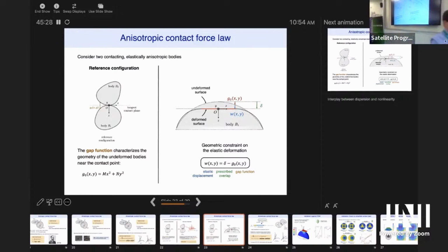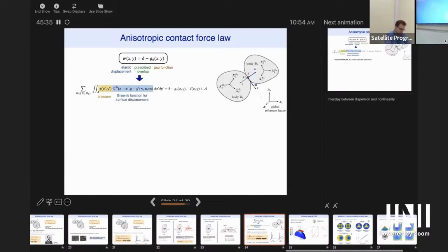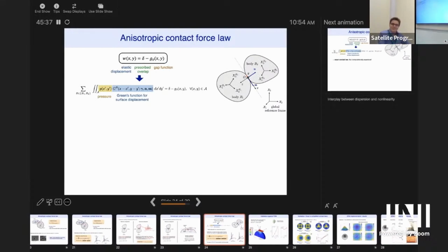Okay, so let's take that and talk about how we would actually solve the elasticity problem. This is the part that I told you I could do quickly. You actually have to do this super brute force. I'm sorry, I really apologize. You have to add the Green's function, and it's an anisotropic Green's function. So there's some Green's function, let's look at particle, say, B1, where you have to imagine that on the surface that you're looking through, there's some unknown pressure distribution.